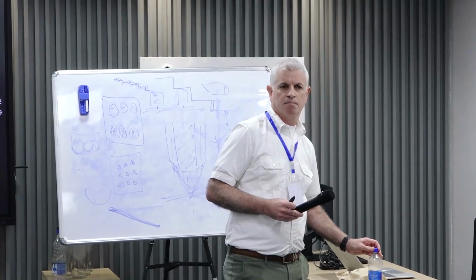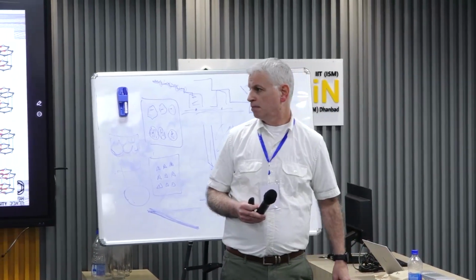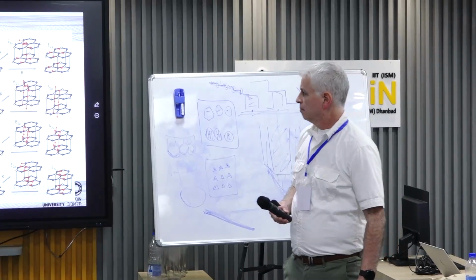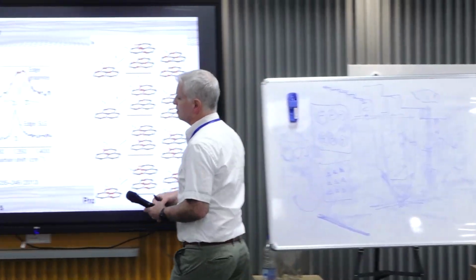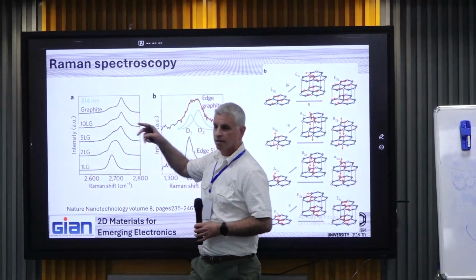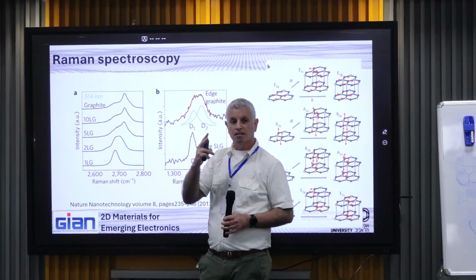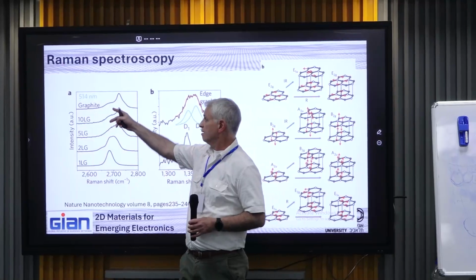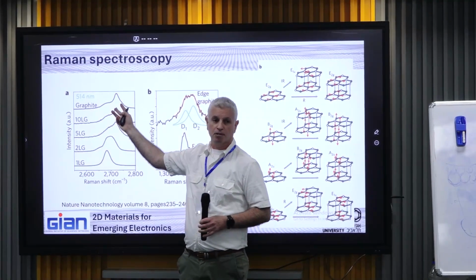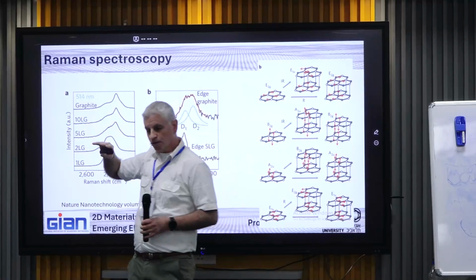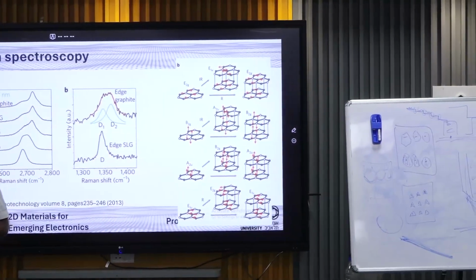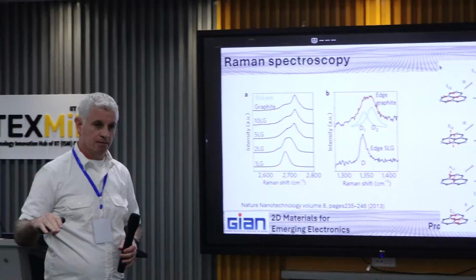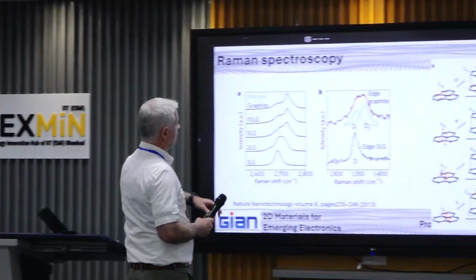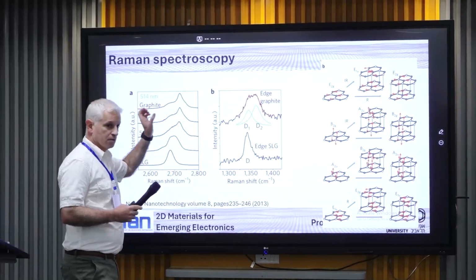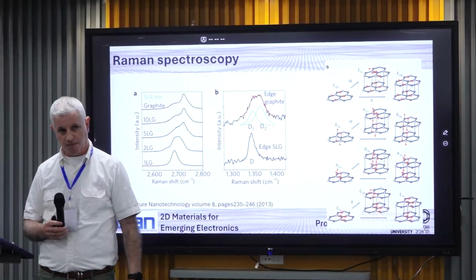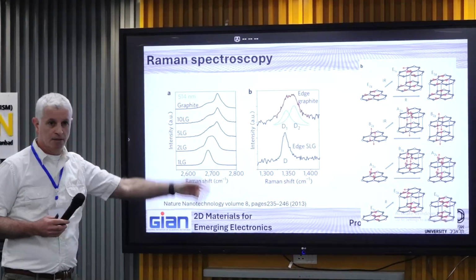Why do you say so? But because the peaks were broadened, right? The full width maximum improved, right? So that's what I'm saying. No, but in this case, the contribution to this peak is coming from several events. Here, there are two different peaks contributing to this G prime. So you cannot compare between that. If you compare, you should also take one of the contributions and calculate the full width maximum. You need to decompose the peaks in the analysis.